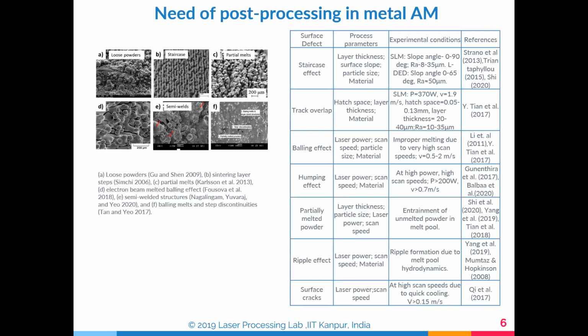Next one is partial melting of the powder. When we move at very high feed rates or lower power, this will form partial melting, and this also leads to some amount of defect. The next one is the ripple effect. Ripples are nothing but something like waves, circular waves, or up and down waves. So for ripple waves, laser power, scanning speed, and material are also part of it. These are all the process parameters. These are all the surface defects. All these surface defects have to be covered by a process which is extensively used for finishing.